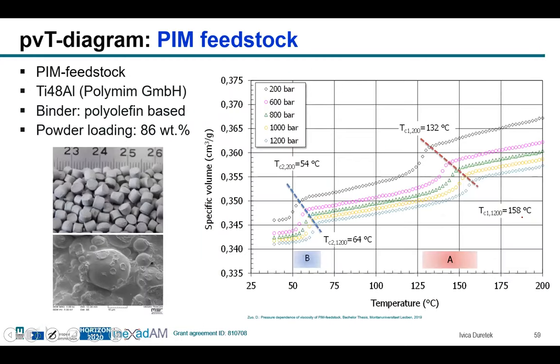In the other case, if you use powder injection molding feedstocks, that means the polyolefin filled with metal particles with a powder loading, for example, of 86 weight percent, you can estimate exactly the different transition temperatures, and you can analyze the binder system. You can see that in this case, we have two different polymers, one part with a melting temperature of 130 degrees and the second one in the range of 50 degrees.